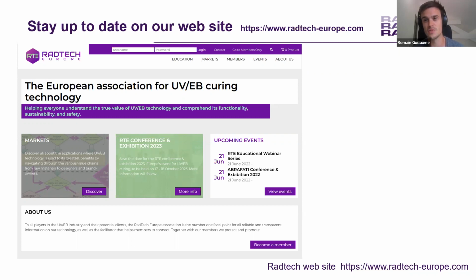So we are mainly in the UVC, and this lamp is able to cure the interface and to create some microstructures in order to get this matte effect. It's also a perfect solution to get anti-scratch or anti-fingerprint varnish. In general, we combine an excimer lamp to cure just this thin layer, so we speak about 100 nanometers, to create this mattification effect. And then we use a mercury lamp to cure the complete coating. But again, that was not presented in this webinar. If you want to know more, you should contact us later on to go deeper into that.